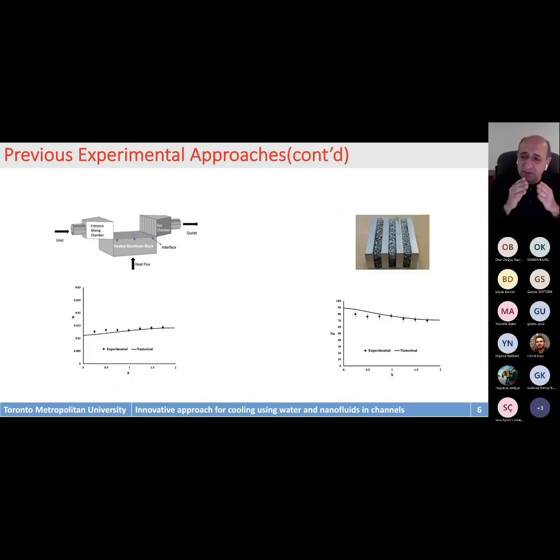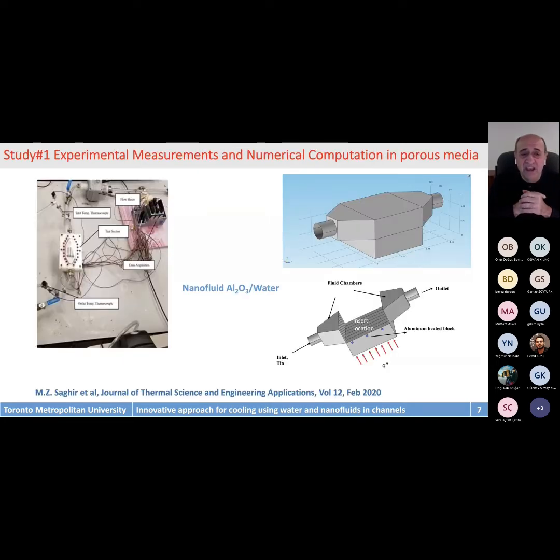We also put some porous media inside those channels, and then we did some experimental work as well. Again, depending on the permeability, and here it's aluminum with a porosity of 0.9, we're able to extract more heat than regular flow in a channel. Then from it, I would like to start taking you slowly into the four studies which we did. One of them is where we tried to use nanofluid, and here we use aluminum oxide with water, and we had different types of application.